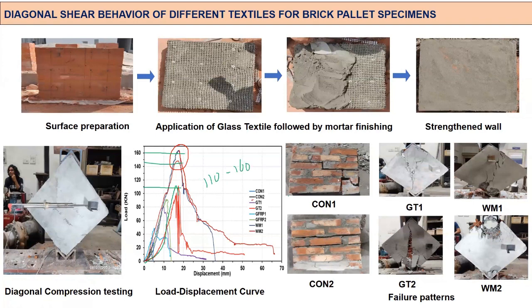Okay. So now, not FRP. This is welded wire mesh. Welded wire mesh, right? So this is the conventional failure pattern, and this is the textile failure pattern. This is the textile. The textile ruptures exactly in the middle, and lets the sample behave like this. And with welded wire mesh, we experienced the crack like this in this pattern. And in some cases, we got a crushing failure also with reference to the strength of your welded wire mesh.